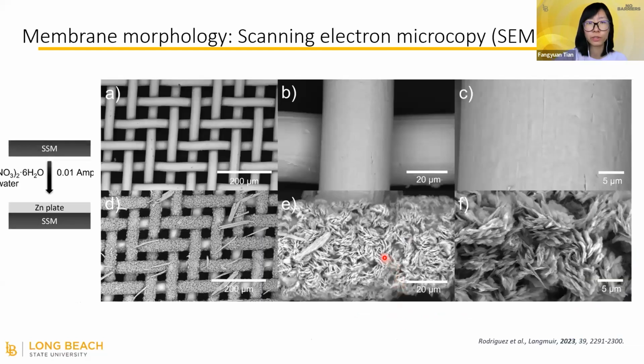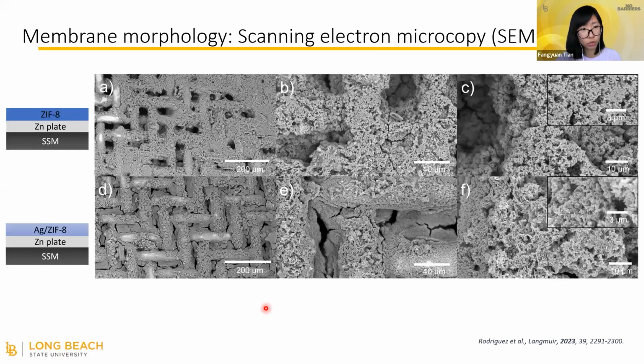This is how the surface looked like. This is a bare stainless steel mesh. It looks very smooth on the surface, without too many features. After the zinc plating, you can see that we have an interesting layered structure, and we found out this is a zinc nitrate hydroxide crystal. Even after 10 minutes, we could have a pretty thick coating on top of the stainless steel mesh.